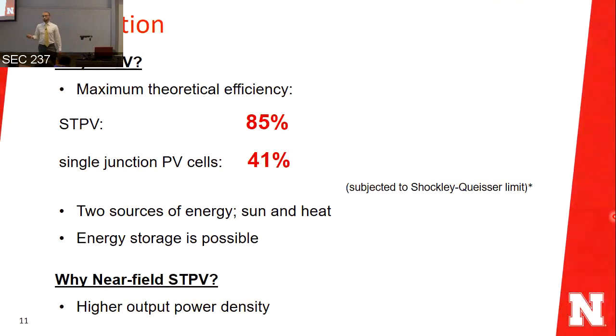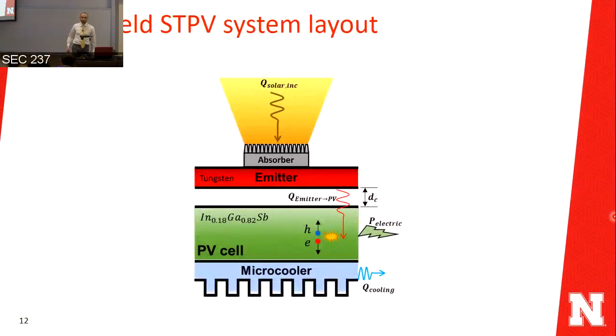So why do we use solar thermophotovoltaics, not just the usual solar photovoltaic? It has a maximum theoretical efficiency of 85%, which is way higher than the single junction PV cell of 41%. And it has two sources of energy. It can be powered by sun or by heat. And energy storage is possible with this kind of devices. The problem is that they have lower energy density. So if you introduce near field thermal radiation, you can expect to increase the energy density of those devices.